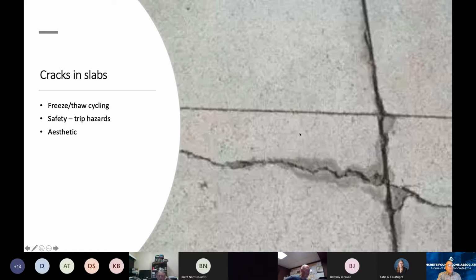But what happened in this particular case is that that slab joint was just far enough, and it wasn't quite deep enough. And so the modulus of rupture of the concrete was sufficient that the crack ended up right here. And it probably initiated right here where it had friction hang up with the adjacent slab section, and then it began to work off to the left until it raveled up and found the horizontal joint that we're looking at, and then it probably cracked and continued on across that.